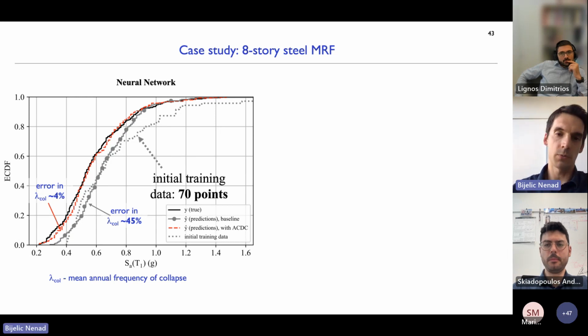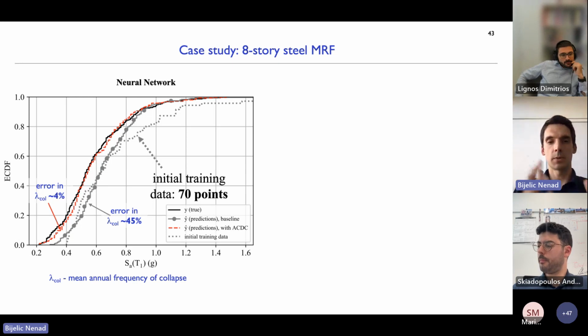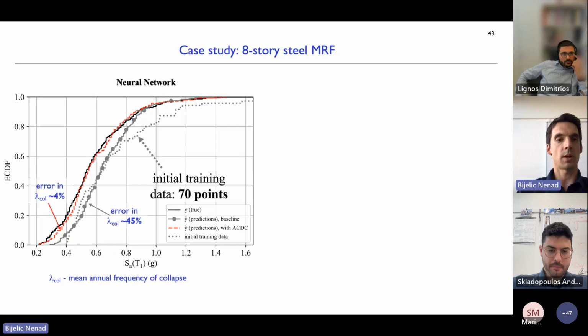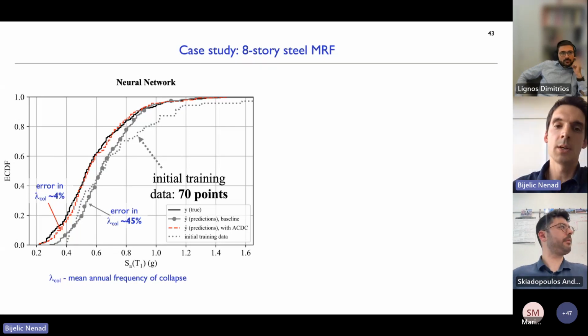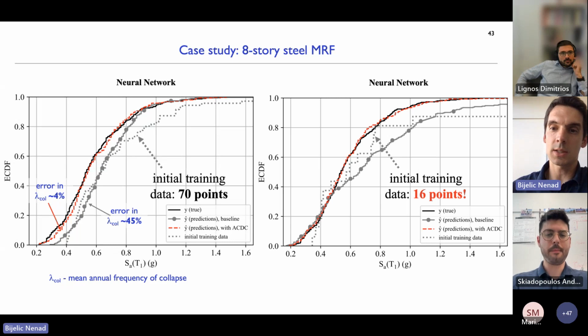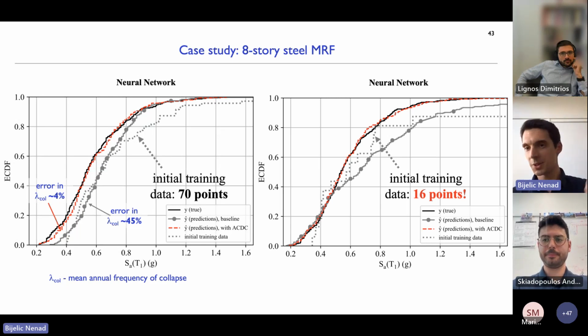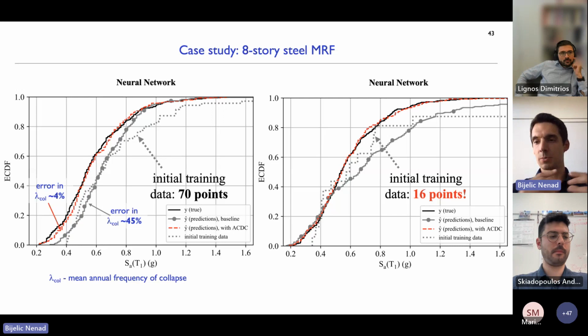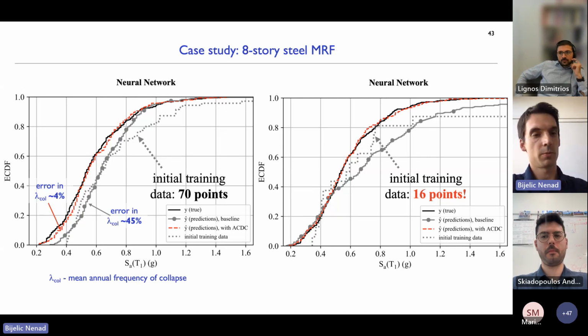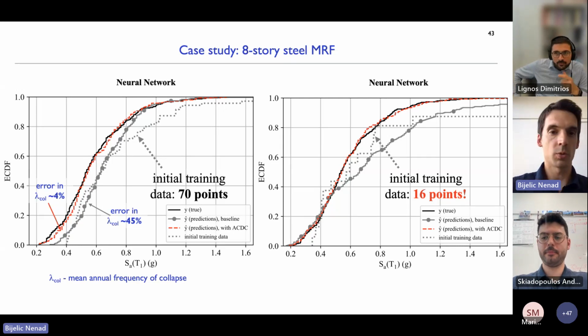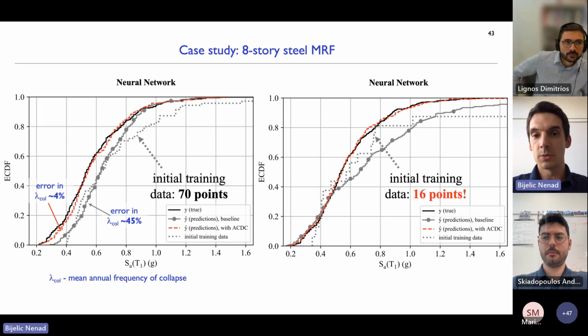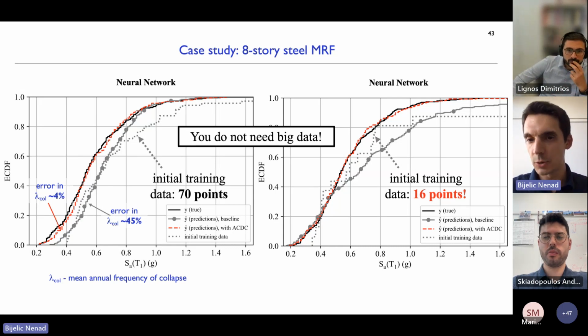Also, final slide: our initial training data here contained 70 points, meaning 70 collapse capacities obtained using IDA. And past studies that we and other people have done suggest you need 40 or more ground motions to get robust collapse predictions. So what we did is also take 16 data points, and we trained a neural network with 16 points using this procedure with augmentation, and we get performance such as shown on the right, which is pretty cool. Takeaway being, you do not need big data. They have been lying to you.